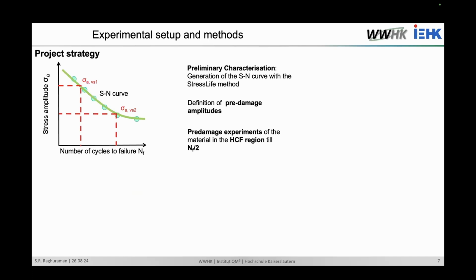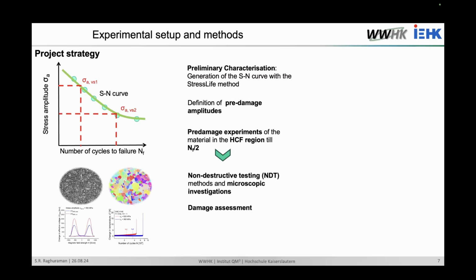So our project strategy is to start with generation of the S-N curve using the stress life method, and then define the pre-damage amplitudes, the point up to which I can damage it partially. Then we conduct pre-damage experiments in the HCF region until half the lifetime. After the pre-damage experiments, we monitor the damage. We quantify the damage using NDT as well as microscopic investigations.